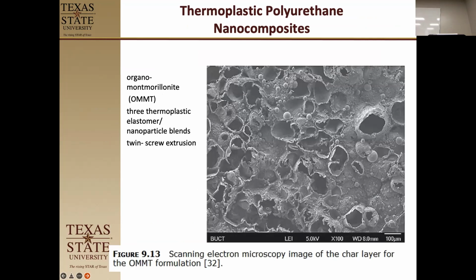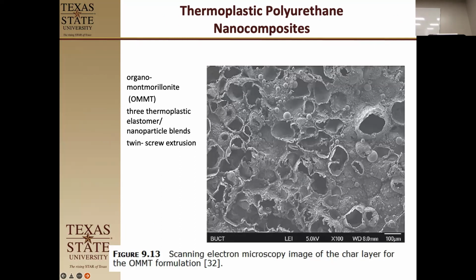with, instead of the nanosilica, the organo-modified montmorillonite. They actually ended up using that to blend it into a twin-screw extruder. So it's processed through the extruder at a low enough temperature to vulcanize, and then baked out in vulcanization. And what they see here is that the structure is a lot different. The actual silica starts to melt and flow on the surface. And again, this is from the top. If you go back, we have a nice, almost uniform flat surface with the nanosilica, but with the montmorillonite, which is an aluminosilicate, we have a different structure to it. You can almost see on the edges maybe where the montmorillonite is starting to aggregate and gather together, because all the other stuff is burned away.